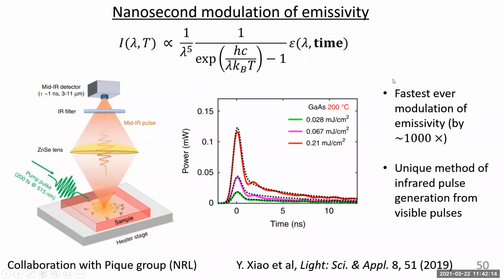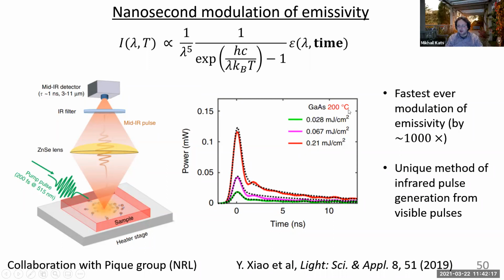Thank you. Yeah, so I'm showing you here gallium arsenide, just undoped gallium arsenide, where the carrier recombination time is about 3 nanoseconds or so, and that's really what guides this decay. We also did these measurements on undoped silicon, and then you have a much longer decay time. So the pulse has a very long tail. And you can imagine playing all sorts of games, right? You can dope, and that changes the relaxation time, the recombination time, I should say. We did not here, but yeah.